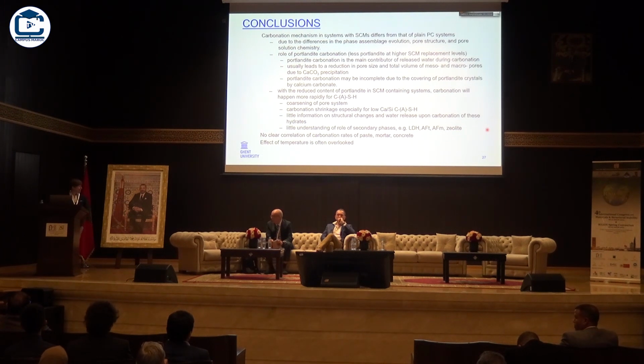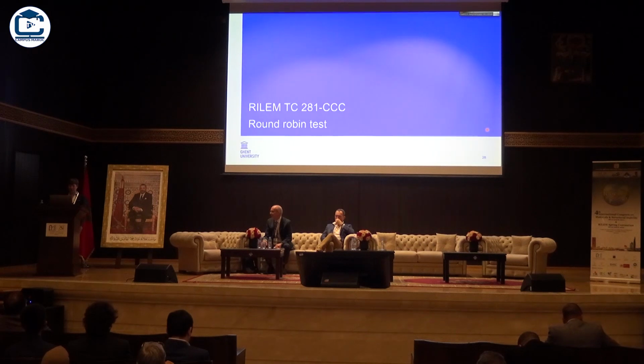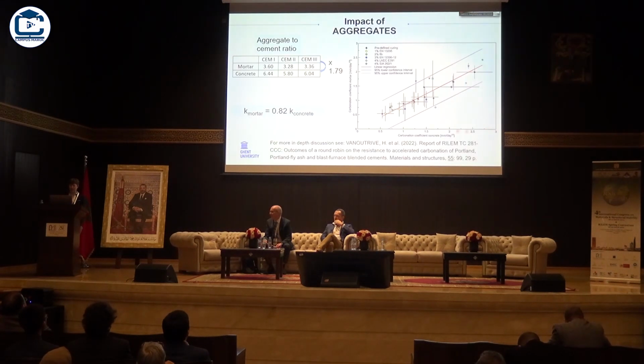Well, actually, I think time is running out. I had a short overview also of our interlab comparison that we have made, but I will keep this for a future presentation. Maybe I will just scroll to the end so that you can see also the reference of this publication. And maybe just for the ones who are interested in the difference between mortar and concrete, I want to add that this interlab test also sheds some light on this, because here in a test with samples that were analyzed by over 17 laboratories, we found indeed that the carbonation rate of mortar is smaller, about 80% of the one of concrete. So thanks for your attention.